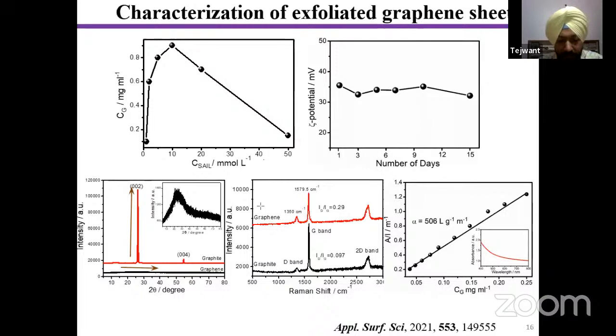Another interesting feature for graphene is the presence of inherent defects. This is the Raman spectra comparing graphite and graphene. You can see I have written D and G bands. The band which appears in the Raman spectra at around 1385 per centimeter corresponds to the D band, and the one at around 1600 per centimeter is the G band. The ratio of the intensity of the D band to the G band, ID to IG, is very important. The lower the ratio, the lower the number of defects. You can see in the case of graphene, the number of defects is very low, as the ID by IG is 0.097.